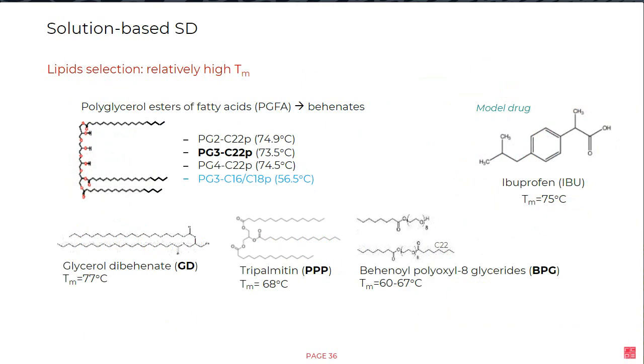So for the solution-based spray drying, as I said before, the selection of lipids with a high melting temperature is very important, and I wrote here on purpose relatively high melting point because lipids in general don't provide so high melting point. So we are talking here about the polyglycerol esters of fatty acids, for example, which are materials with several glycerol units attached to each other. As you can see here in this example, either PG2, 3, or 4 molecules, and then they are esterified by behenic acid. That's why they are called behenates. And this structure provides a relatively high melting point of around 74, 75 degrees.